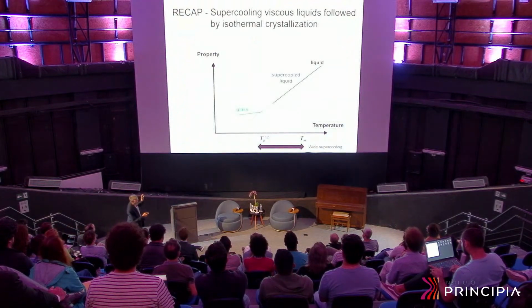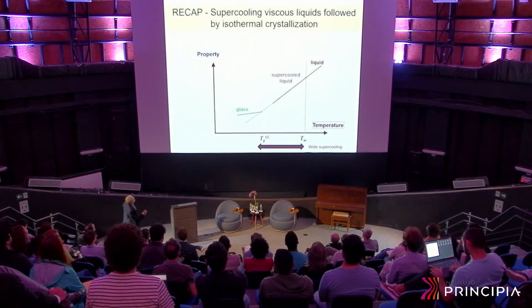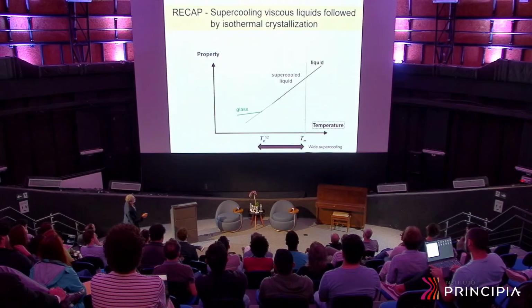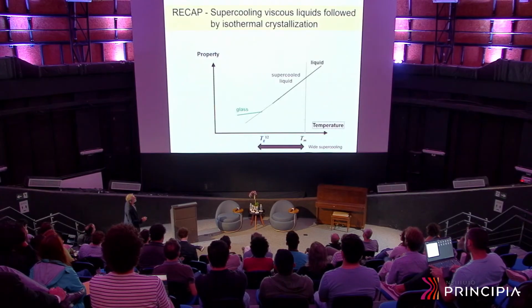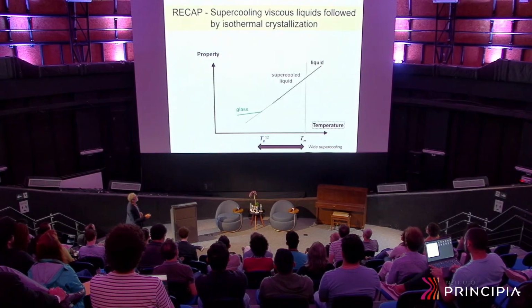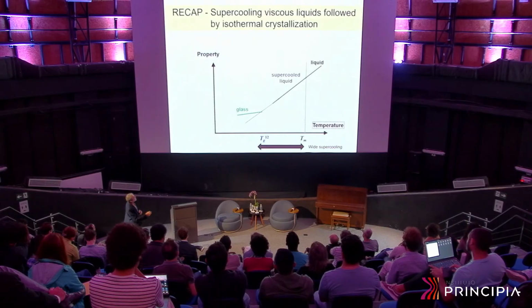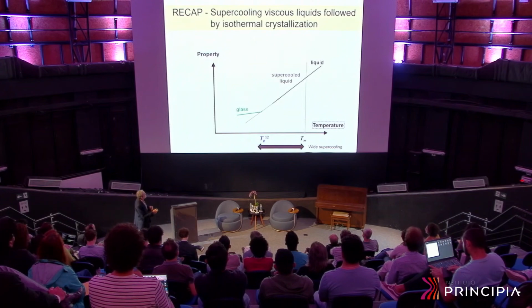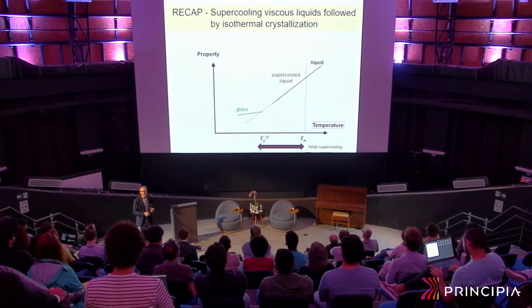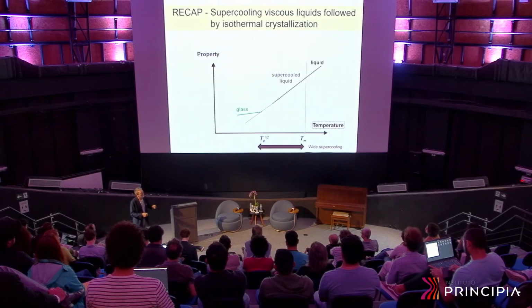This is the most famous plot for glass science. If you have a liquid, it is thermodynamically stable above the melting point. You have a liquid forever, it'll be a liquid forever. Now, if you cool down a liquid, at a certain stage, it will crystallize. Now, if you avoid crystallization by cooling it fast enough, you enter a region called supercooled liquid. This is a metastable state. I mean, this supercooled liquid would love to crystallize, but it needs a certain time. If the cooling rate is fast enough, it will not crystallize.